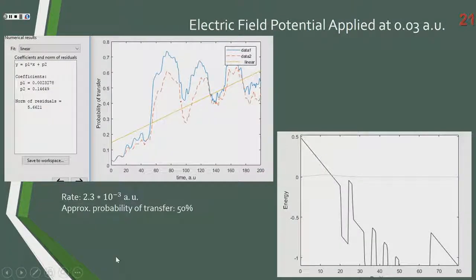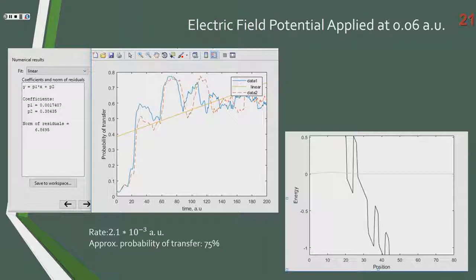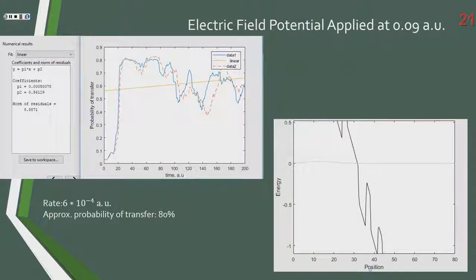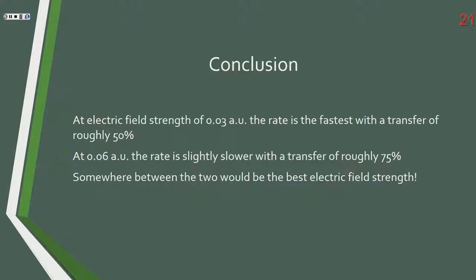Increasing it to 0.03 AU, the rate increases and so does the transfer. Increasing it to 0.06, the rate decreased a little bit, but the transfer still increased. And at 0.09, the rate is its slowest, but the probability of transfer is at 80%. So in conclusion, at an electric field strength of 0.03 AU, the rate is the fastest with a transfer of roughly 50%. And at 0.06, the rate is slightly slower with a transfer of roughly 75%. So depending on what you're doing and how long you want to wait for it to fully transfer, the higher strength of electric field gets you a higher transfer, but you're going to be waiting longer.